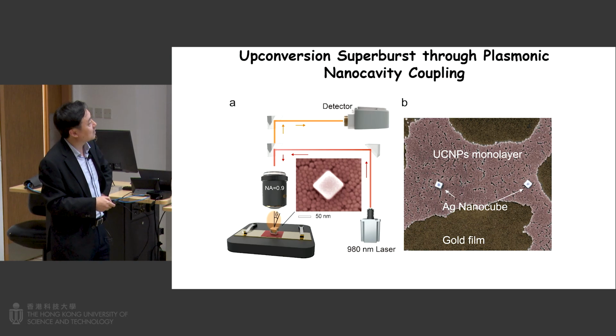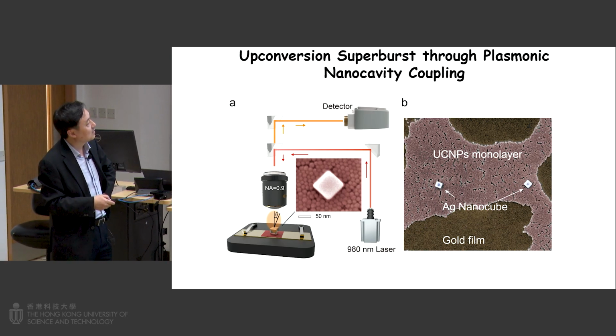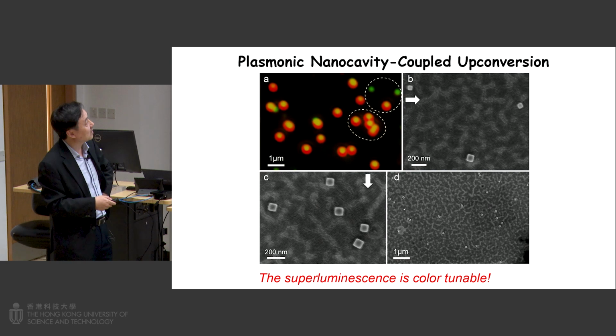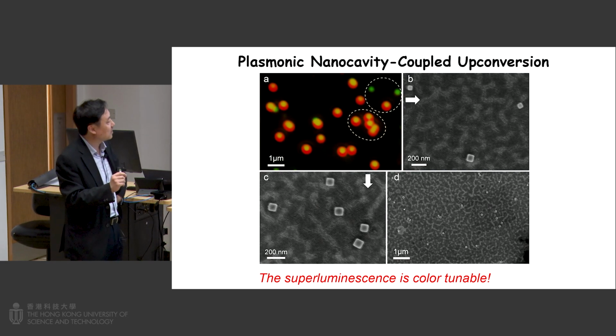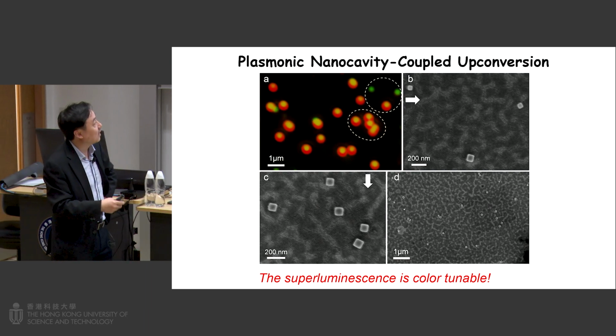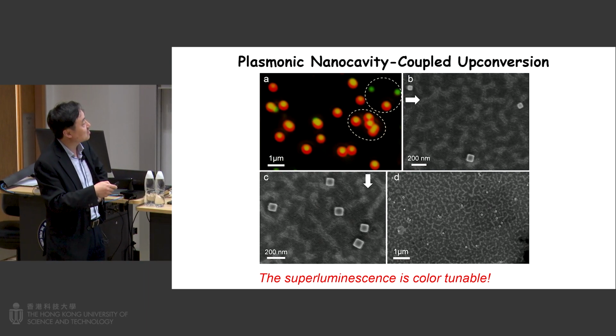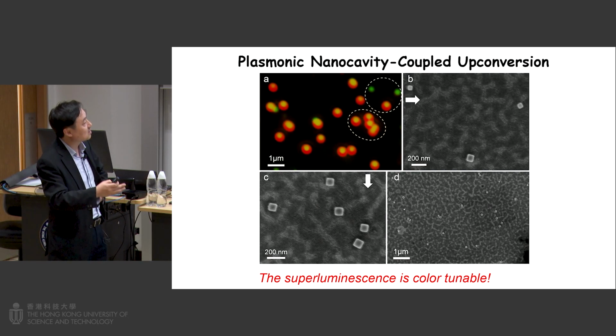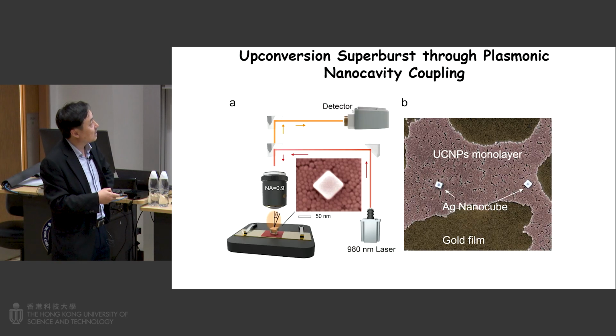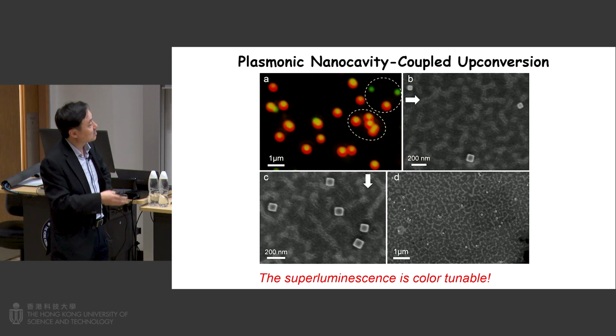I want to show that this is real experimental data. You can see pretty uniform upconversion, more or less. We have this single silver nanocube, and underneath the nanoparticle monolayer is the gold film. Based on this design, we look at the luminescence enhancement. But a very interesting discovery is that we can also use this sandwich design to control the upconversion luminescence colors. You can see the color can be tuned using this sandwich design. I think this nanocavity design is very interesting, not only for upconversion materials, even for quantum dots, perovskite nanocrystals. We can certainly try other materials.